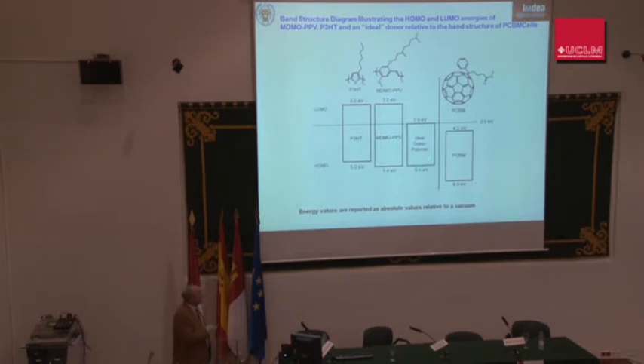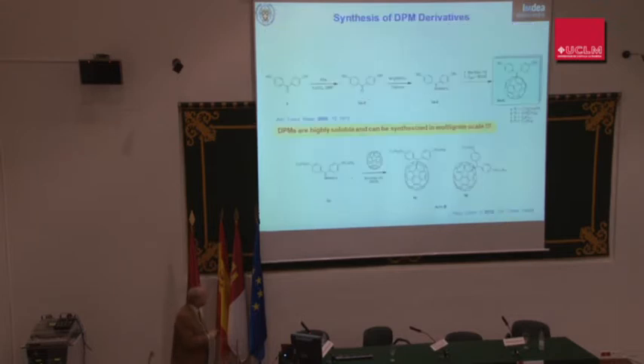The parameters you have to control are the HOMO of the polymer and the LUMO of the acceptor, and this controls the VOC of the photovoltaic device. And look at this: if you have this level too high, you are losing a big quantity of energy. It has been proved that 0.3 electron volts is good enough as the driving force to promote the electron transfer from the donor to the acceptor. I will not go into more detail on this.